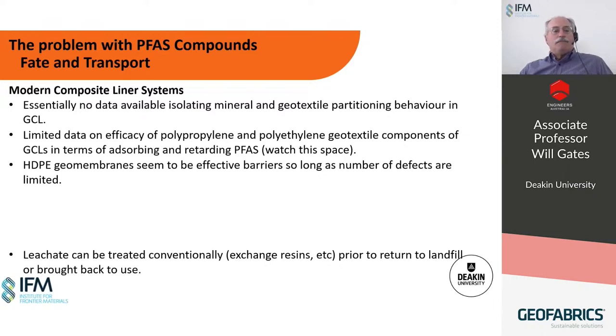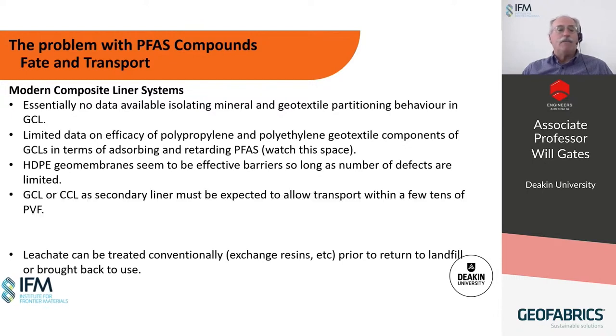Most of the lining systems that have been developed did not have PFAS in mind when they were developed. They do seem to have, for example, HDPE geomembranes do seem to have fairly good effectiveness. So we're at least lucky in that regard. I think it's really important to point out that the geosynthetic clay liners and compacted clay liners should only be considered as secondary or even tertiary lining components in the protection of the environment against PFAS from landfill leachates.